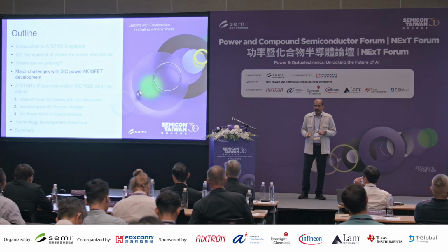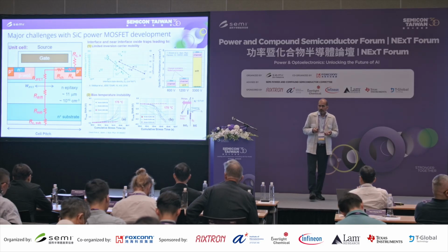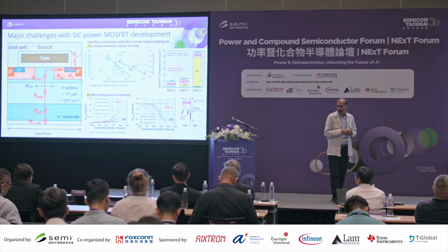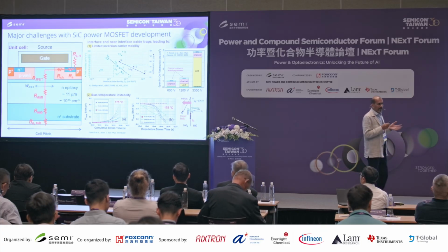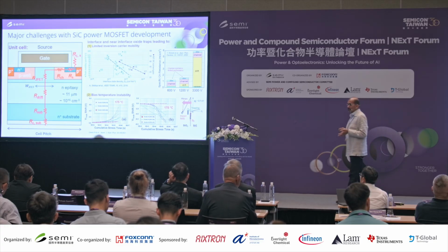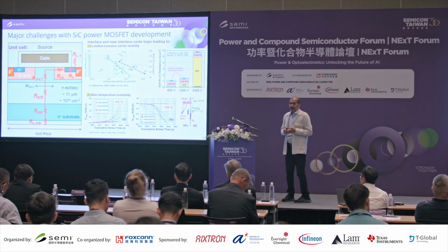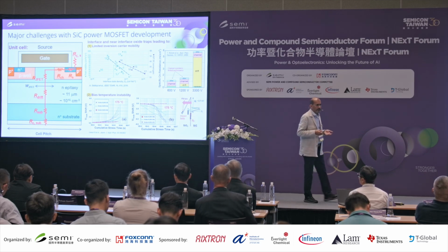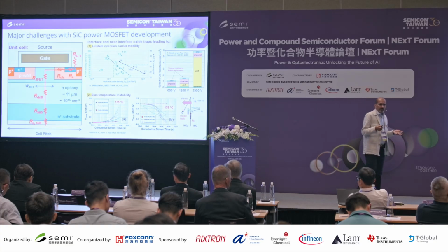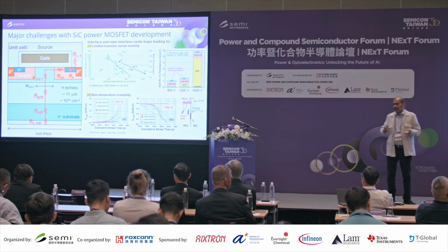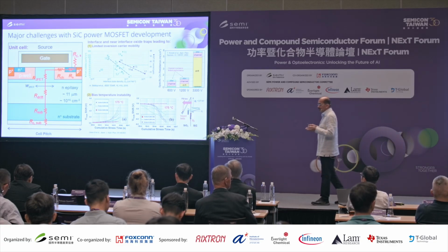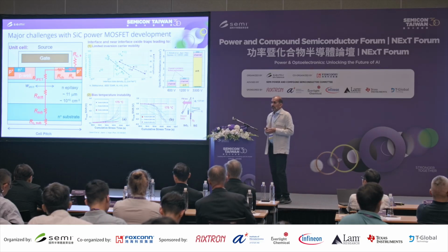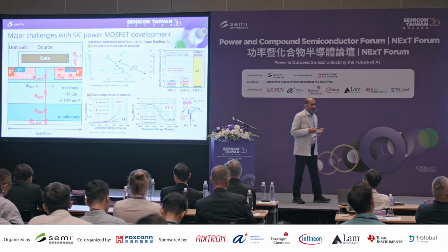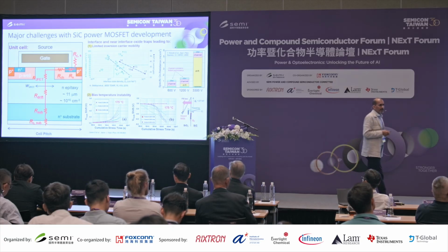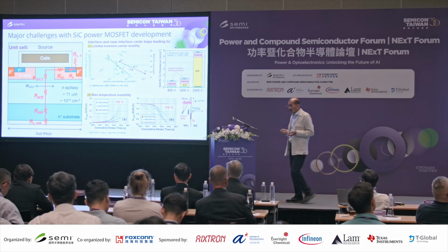Let me talk about the major challenge in silicon carbide, which has been our focus. One of the major challenges is poor MOS interface. Our line is a MOSFET line, making transistors, right? The MOS transistor requires a very good quality MOS interface. In silicon, the MOS interface is nearly perfect, with Dit values in the high E9 range. In silicon carbide, if you just oxidize, the interface trap charge values are in the E13 range, at least 3 orders of magnitude higher than silicon, because the carbon coming out of the silicon carbide matrix is creating problems.